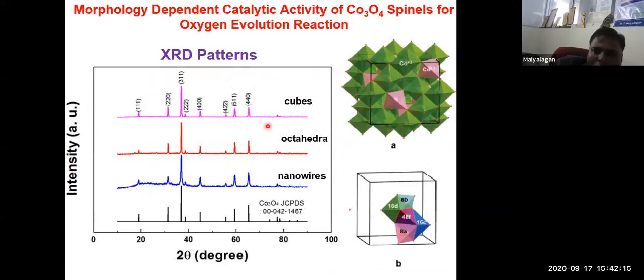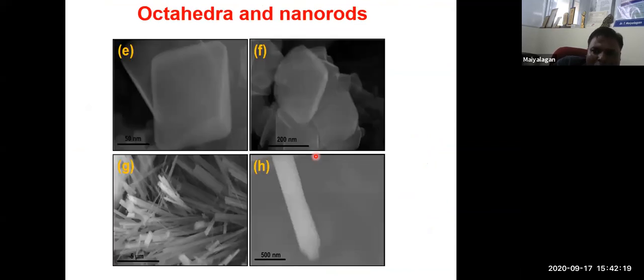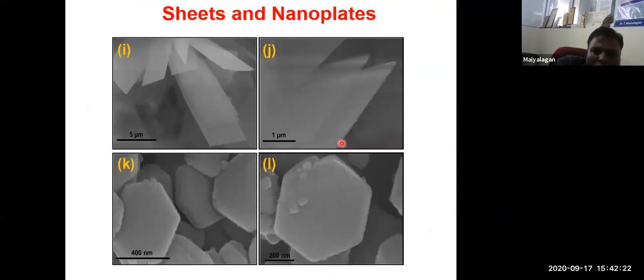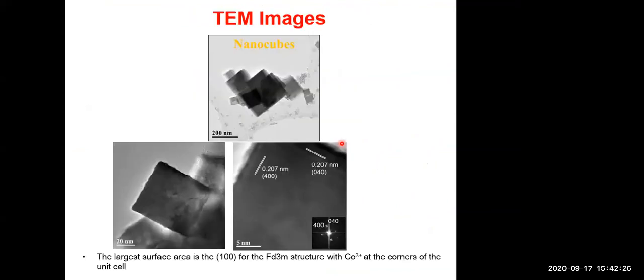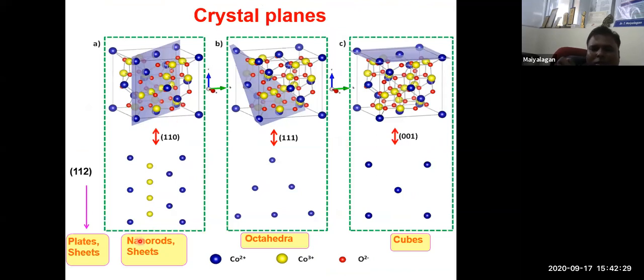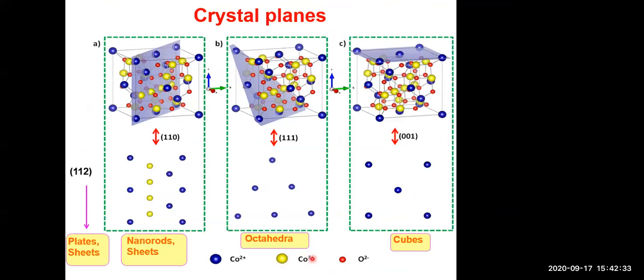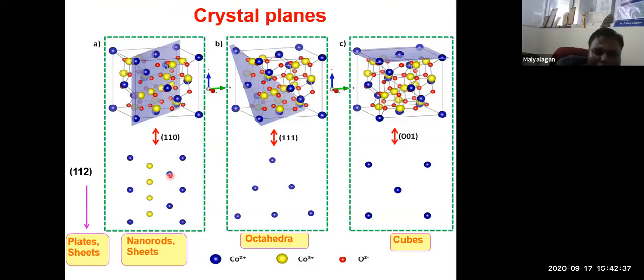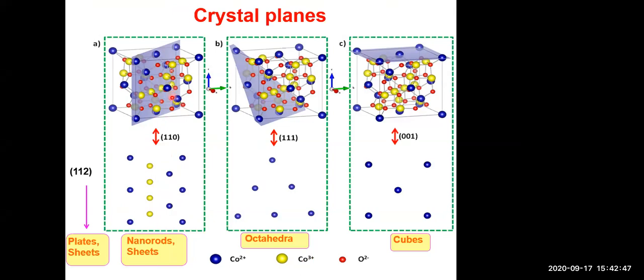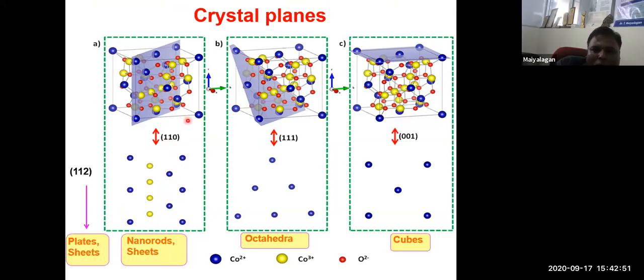When you take cobalt oxide spinel, you can have different structures like cubes, octahedra, spheres, rods, sheets, hexagonal planes, and nanocubes, as in the TEM images. Cobalt 3+ is more important for OER. The nanorods on sheets have more cobalt 3+ on the 110 plane for this particular material. It depends on the material which plane is oriented and what the active sites are. The cobalt oxide 110 plane shows more 3+, which is more essential for the oxygen evolution reaction, so this plane is particularly good. You can change the oxidation state, change the planes, and see the activity.